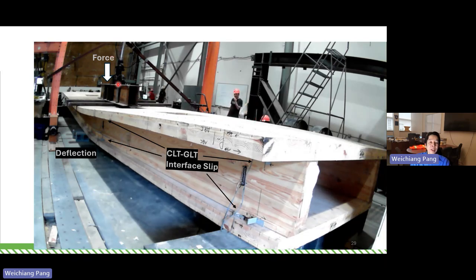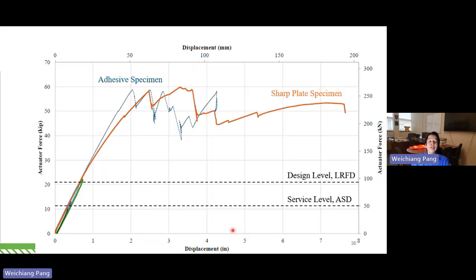We have an actuator pushing down here with the loading bar spread out. So you can think of this as a 2-point load system, or 2-line load system, at the midspan. We have LVDTs and string pots at different locations to measure the interface slip between the CLT panel and glulam, near the midspan and near the end. We also had string pots to measure the deflection at the two sides of the cassette floor system. We also have something to measure the deflection near the support, so we can take out the bearing crushing near the support here, right?